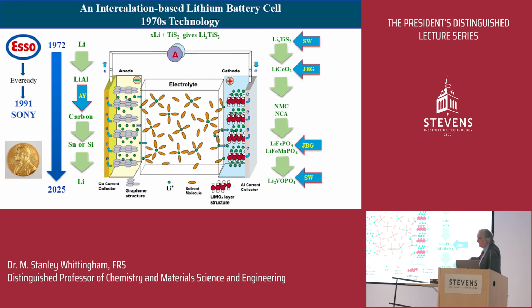All very expensive, so a big pushback now to go to lower cost materials, and it was John Goodenough again who discovered that lithium iron phosphate, a common mineral, would work. You can get lithium in and out of that. Very poor energy density. So a lot of us are now trying to improve it by putting manganese in there instead. Or as we're doing in our lab, we're trying to put 2 lithium ions in to make up for the low energy. And I promise I'm not going to show you much chemistry today.